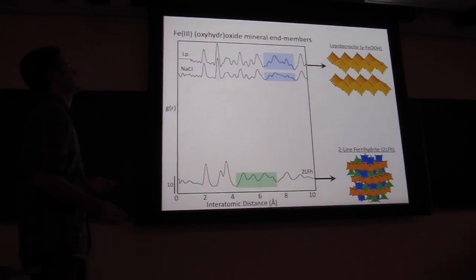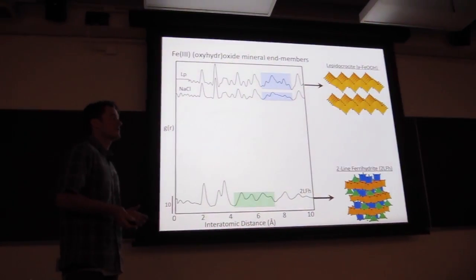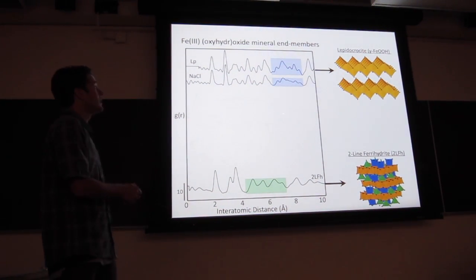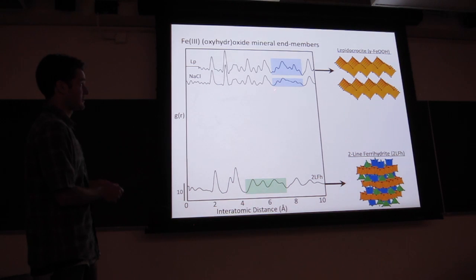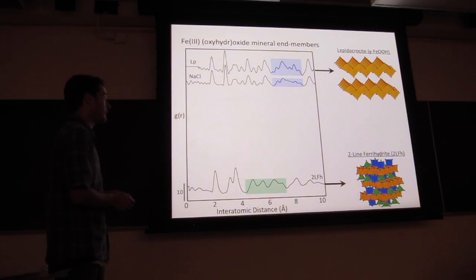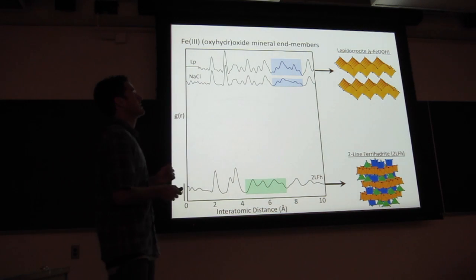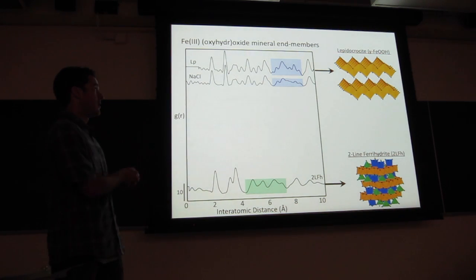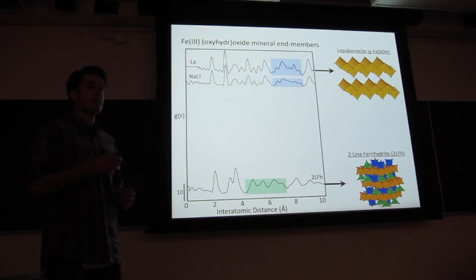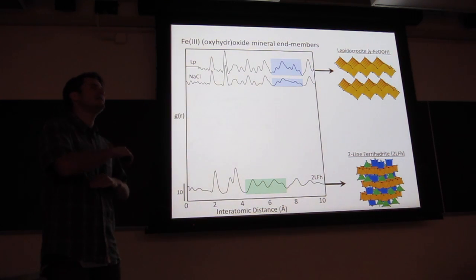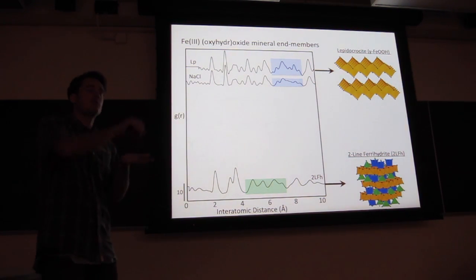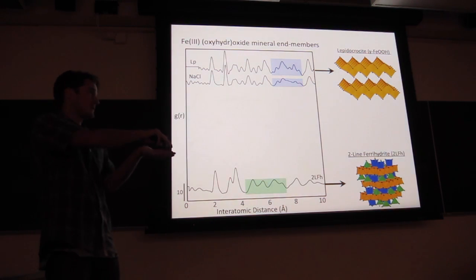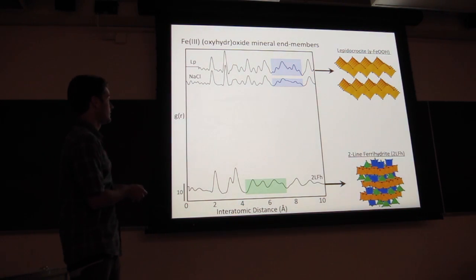So in our simplest system, something like sodium chloride, an electrolyte that has no strongly sorbing oxyanions, we get lepidocrocite. I highlighted the fingerprint for lepidocrocite in blue and the fingerprint for ferrihydrite in green. You can notice that there's some deviation in the line shape, especially with this peak here at 8.6 angstroms. That's actually because in our system, when we generate our most crystalline material, we generate lepidocrocite with poor sheet stacking order, meaning that there's only a few of these edge-sharing sheets stacked on top of each other.